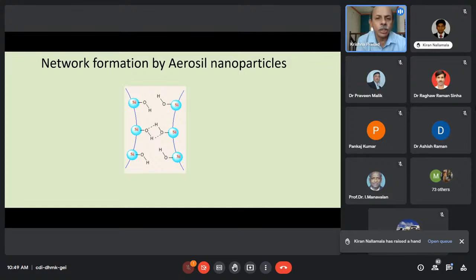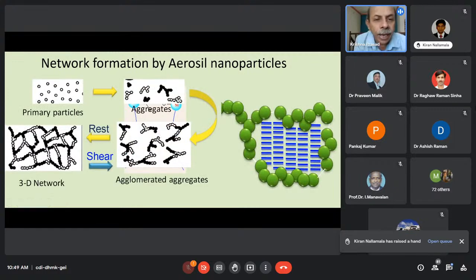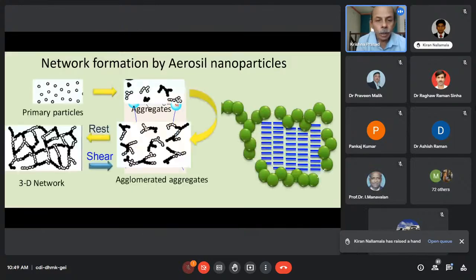And these Aerosil particles are silica particles having, for example, SiOH surfaces. And it is the presence of OH on the surfaces. So two different particles, I have put two different particles here in the proximity of each other. The OH can form a hydrogen bond depending on the proximity of the two particles. And this gives rise to, for example, aggregates of the particle. Particles can come together in a few number, or they can form agglomerated aggregates, or finally, they can form a 3D network altogether.